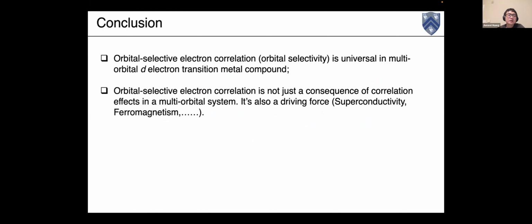And then this is my conclusion for all the three studies that we have done. I think this orbital selective electron correlation effect is universal in these multi-orbital d-electron transition metal compounds, not just the iron-based compound we mentioned, but also the three-dimensional pyrochlore lattice, which has 3D orbital bands, and also the pnictides.